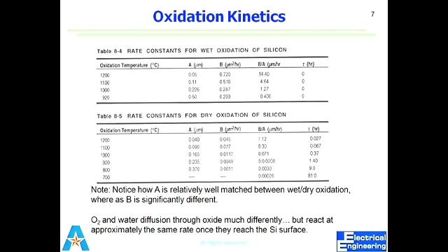So what usually people do practically in labs or even in industries, let's suppose I need 2 micron or 1 micron thick layer of oxide. If I need 1 micron thick layer of oxide, I know that if I use dry oxidation, the quality would be good, but it will take more than 24 hours for 1 micron. So you cannot put it inside the furnace for so long.